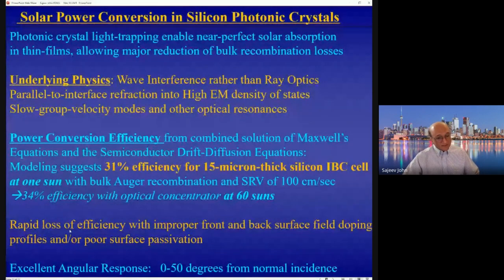And I should emphasize that it very much depends on the surface passivation. There's a very rapid loss of efficiency, as there would be for any solar cell with improper front and back surface doping and passivation. In fact, you can reduce this down to 5% efficiency if those surfaces are not passivated at all. And finally, another very nice feature of photonic crystal solar cells is that they exhibit very good angular response from normal incidence up to about 50 degrees off normal without losing much of the efficiency. So with that, I think I'll stop and take any questions if there are.